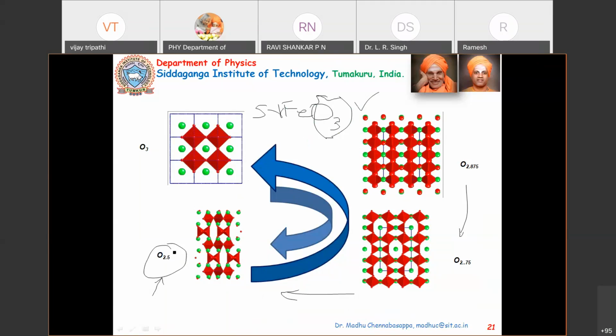I can go from 2.5, which is your orthorhombic, to a more symmetric or highly symmetric phase, which is your cubic. Okay, O3 is cubic. These are things you can study, and based on the oxygen concentration, your physical properties would change. Okay, so this would be more ferromagnetic, and this is very weakly magnetic. So this is an antiferromagnetic structure.